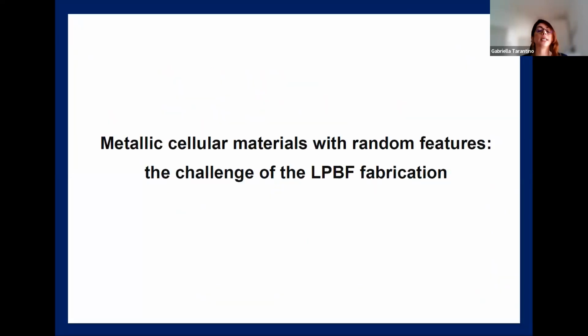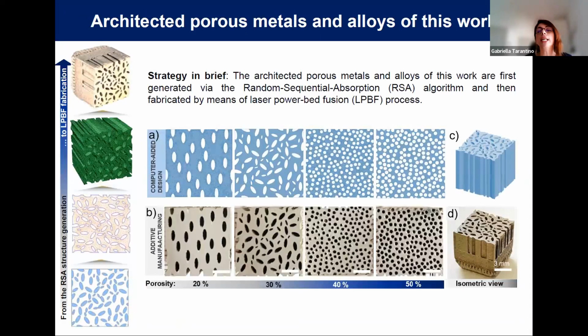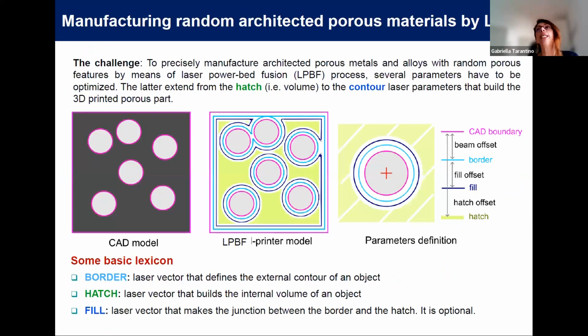Now you have seen that I presented the general algorithm for the 3D version of this metamaterial, but when it comes to metallic 3D printing, our material contains closed pores. And that's essentially a challenge when we go to the laser powder bed fusion fabrication. So essentially, the solution will be the 2D version of this material, which allows the fabrication by metallic additive manufacturing. Our material contains pores which are through thickness, and is essentially designed with the same algorithm in the 2D version.